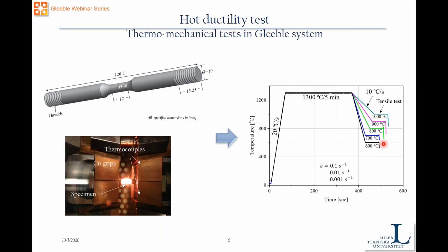In this case, we were performing static tensile tests at different temperatures, which cover more or less the temperatures that we saw previously. The tensile tests were performed from 600 degrees up to 1000 degrees, with 100 degrees in between as a step. We were also applying 3 different strain rates, trying to simulate the effect of the casting speed, taking into account that the lowest strain rate here replicates the real casting speed applied in the real process.